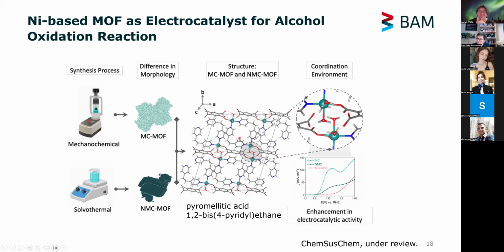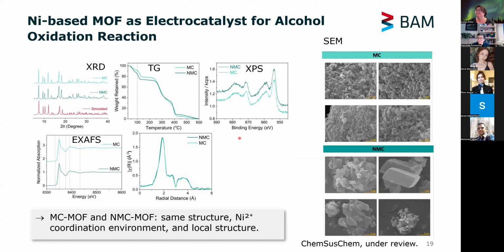And we were looking into the alcohol oxidation reaction in that case, but at the first test we were checking whether we have the same material. And you can see here from these data, you can also see that our institute has most of the techniques available. So we also tried to have a complete set of characterisation. So that's X-ray, of course, then thermogravimetric analysis, and also XPS and XAS, which shows us that we have in this case nickel in +2 state, and really there is not a big difference in these materials from a structural level,